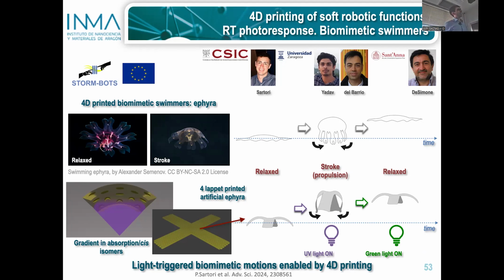And we have tried to mimic this structure by 4D printing, by 3D printing with our photosensitive material, taking advantage of the fact that when we irradiate with UV light, we have a strong absorption in our film. So light is primarily absorbed in the first layer and does not reach much to the top layer. So we generate a population of these non-mesogenic molecules in this region, and all-trans molecules in this region. So the system, to accommodate these stresses, bends towards the light source. By doing this, we expect to have this swimming motion, and by using green light, we want to go back to the initial state.